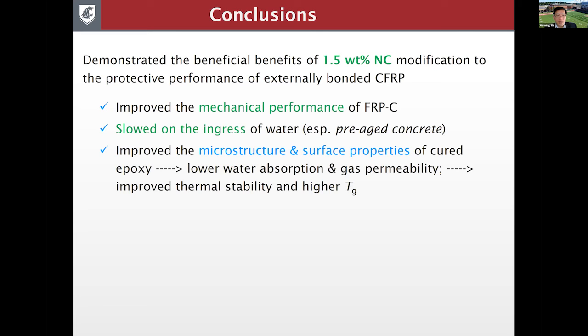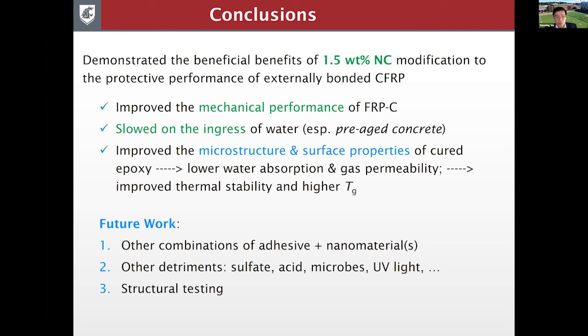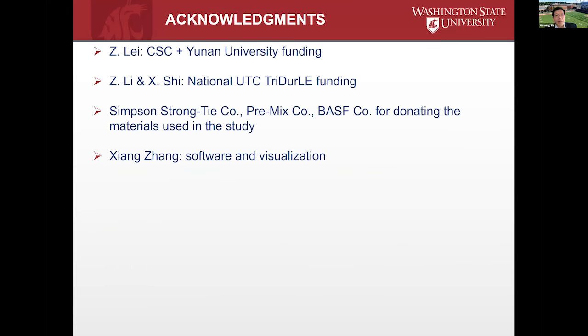And the reason is that this improved microstructure and surface properties of cured epoxy, resulting in lower water absorption and lower gas permeability. And also the nanoclay had additional benefits in thermal stability and higher glass transition temperature. In terms of future work, we envision that there could be other adhesives or other nanomaterials or more than one type of nanomaterial to be investigated. And in addition to salt scaling, one could look into other surface environments in terms of sulfate, acid, or microbes, or UV aging. And again, starting from molecule level to materials level to structural level testing.